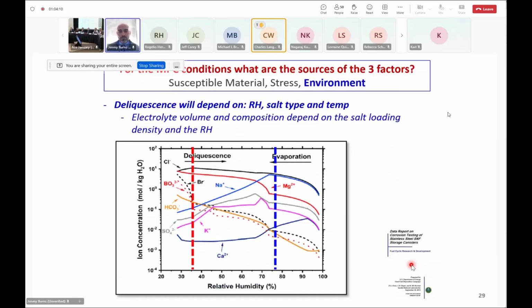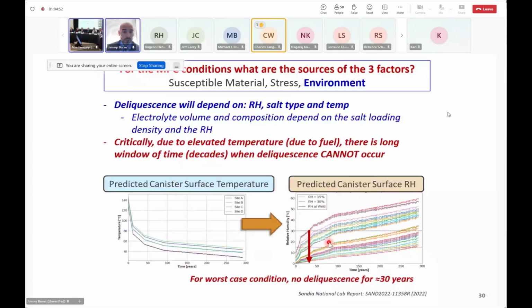And then the electrolyte volume and the composition is going to depend on how much salt has deposited and the relative humidity. And so again, examples of that are shown here, to where your ion concentration, or your concentration of your salt, is dependent on the relative humidity and the salt loading density. The reason I bring these up and show these plots is just to give an example of the depth of study that has been done to try to understand this damage mechanism and the propensity for this damage mechanism to happen. So again, these are just examples. I've just pulled out a couple of charts from a report from Sandia National Lab.